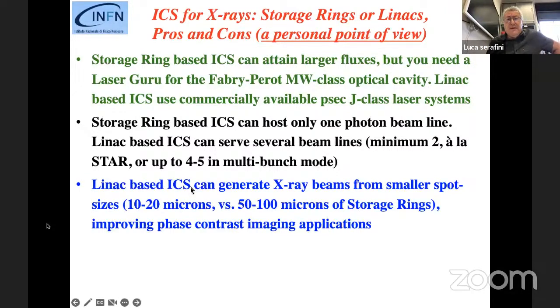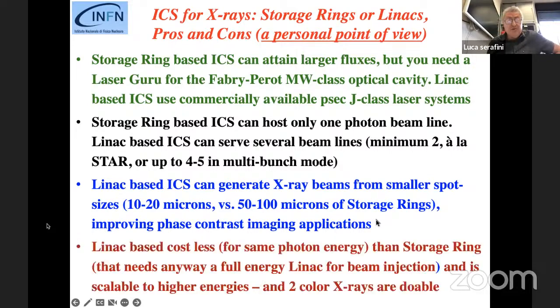LINAC-based ICS, because of the normalized emittance of the photoinjector, are definitely smaller than those of storage rings with this moderate energy. They can operate with smaller spot sizes, typically in the range 10 to 20 micron, while storage rings are in a larger range. And this is important for phase contrast imaging applications, as we know, because the transverse coherence length scales like the inverse of this number. Okay, last but not least, the LINAC-based ICS costs less for the same photon energy, clearly, and is also easily scalable to higher energy.